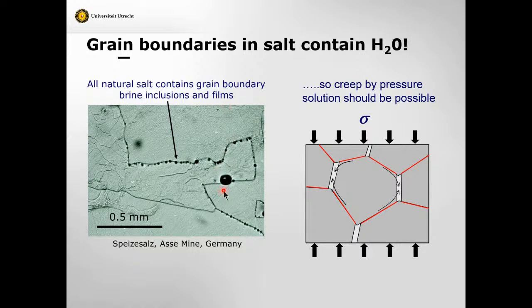this has been extremely controversial in the literature because there is a widespread belief in the engineering community that salt is not soluble in a saturated solution, which is in fact quite wrong. But what do we actually see in natural salt? They contain water. All natural salt contains grain boundary brine inclusions and films between the crystals. Okay, so creep by a process such as stress-driven dissolution at high stress boundaries and diffusion and precipitation should be possible. Dissolved material here, precipitated there. That ought to be possible.